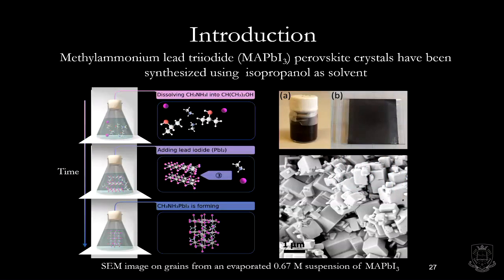Now we go back to the homogeneously grown perovskite crystals. They grow directly in the alcohol solution. Immediately when you mix the different components, you get a black solution instead of the bright yellow solution that you otherwise have, a perfectly dissolved solution which you deposit. Here it becomes black directly, and you form crystals immediately in the solution. So we mix components and we get perovskites. And here is the SEM image of how the perovskite grains can look. As you can see, they have a large deviation in size, but they seem to be rather organized. They are rather sharp at the edges. The cuboidal grains are rather well organized.